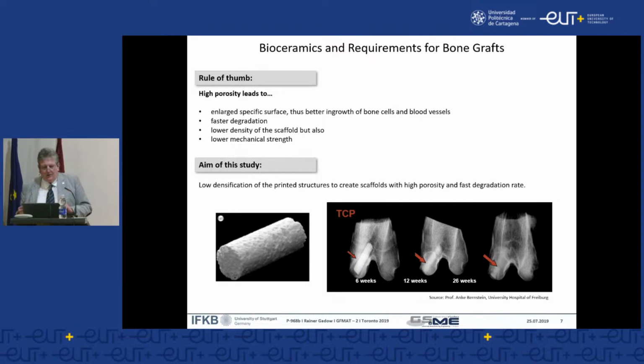And now look, the image left hand, you can clearly see the cylinder. There is a perfectly fit of the bore, yeah? And we can see the cylinder in a good contrast by X-ray analysis. And after 6 weeks, it has not changed so much, but we can see there is no infection. There's no problem. After 12 weeks, you can see that the contrast is weaker and weaker, and the material is resorbed and rearranged. And after 26 weeks,